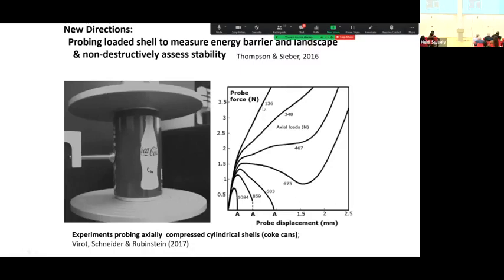So look at this. Here's a load applied to the can. And by the way, this is prescribed end shortening, not prescribed load, but that's the load associated with that end shortening of 136 Newton. And it's probed laterally. And look at the probe forces we're talking about, only measured in newtons. But when the load is very low, you can probe it and it doesn't buckle. But let's look at the other extreme. Here's the same can loaded to over 1,000 newtons. So a Coke can carries over 200 pounds before it buckles. So you can stand on one. Some people can.